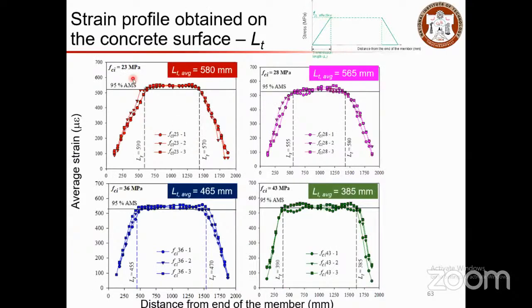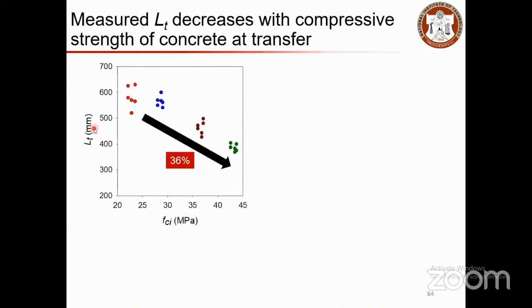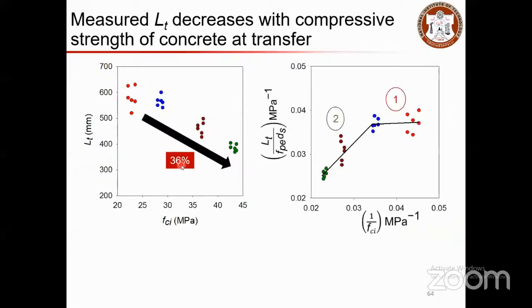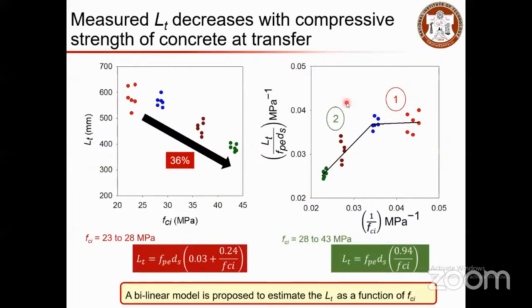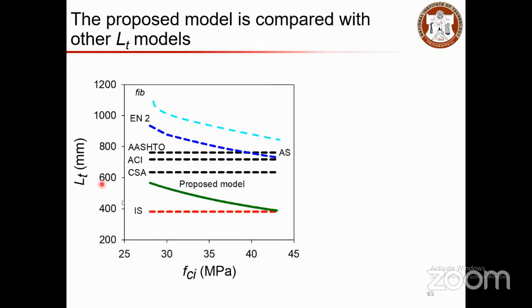And from the obtained results, you can see the 95% average maximum strain method is used to get the transmission length using various strengths of concrete. So it is summarized in this plot. This indicates that when you change the compressive strength, the transmission length is gradually decreasing. So from 23 to 45 MPa of the strength at the time of release, the reduction in the transmission length is about 36%. Likewise, the stress effect is also induced, and from this result, a bilinear model is proposed to the code to enhance the determination of transmission length.